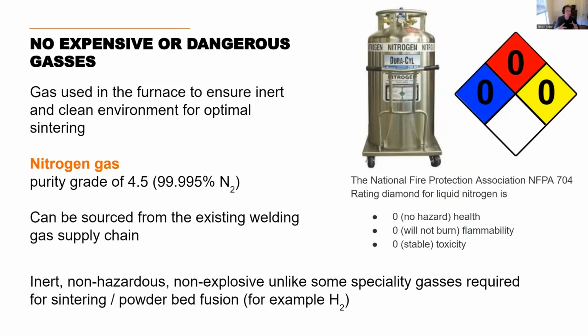This is a very safe and inexpensive gas that you can actually source from your existing welding supply chain usually. It's inert, it's non-hazardous, it's not explosive, unlike some of the specialty gases required for other processes, like hydrogen for some sintering processes or argon or some other materials that can be relatively challenging to work with, or I should say more challenging than the nitrogen gas. The National Fire Protection Association rates this as 0 across the board for all these different health hazards that you're going to want to look out for. So even though there is this little bit of a foreign process of sintering involved, it's very easy to use and uses a very safe and inexpensive gas for that actual sintering process.